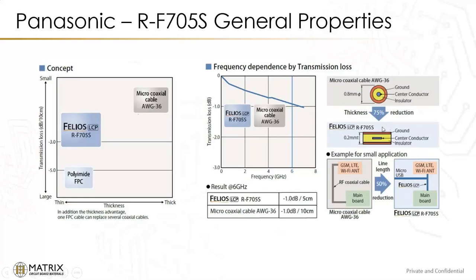If we can come up with a double-sided product that's LCP, you can see that it's 0.2 millimeter in height, so we get a 75% thickness reduction going to an LCP. Then combine that with a shorter line length, and we can approach signal loss that's comparable to an actual coaxial cable. That's kind of where we're headed: to find those applications or people that are looking at replacing a coaxial cable with a high-speed, thinner material.